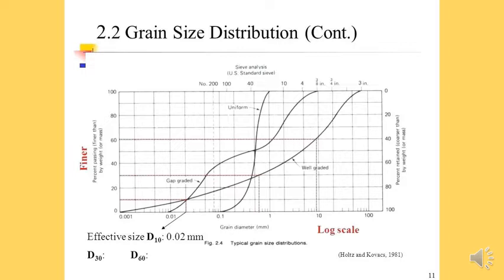Now with the poorly graded aggregate, the uniformly graded aggregate, sorry, all of the aggregate is between 1 millimeter and 0.1 millimeters in average diameter. There's no big particles in it, there's no small particles in it. So we can see that there's no big stones, and neither is there really small silt or clay. This is a very pure sand.